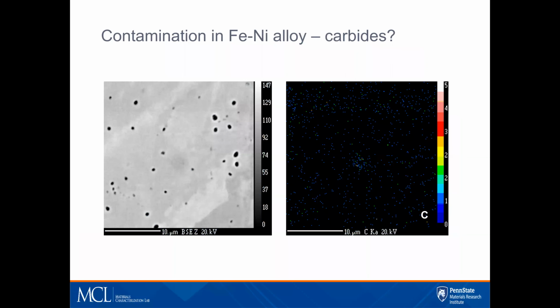This was one that was brought to me, and they were making, this was for a high-end rocket nozzle. And they were seeing these black specks when they were imaging it in the SEM. And they thought it was a carbide inclusion. So they brought it to me, but if you see on the right, that's just noise. The highest count number there is 5, and that's nothing. That's just noise. And so I said, nope, those are not carbides. So what are they?